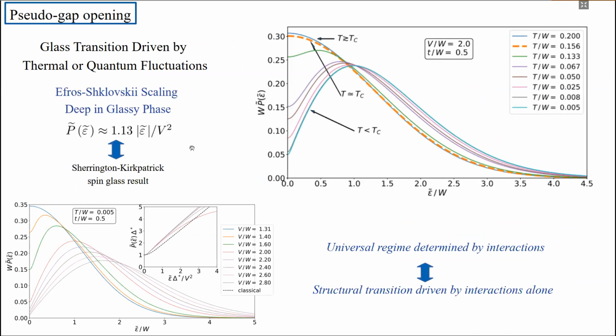Okay, so first let me show you this field distribution P epsilon. I argued that this shows you the presence of the glass transition. And this is depicted here on this figure. So this figure here shows this local field distribution at various temperatures. At high temperatures, we get a Gaussian shape. And this is even true at the critical temperature depicted by this dashed line here.